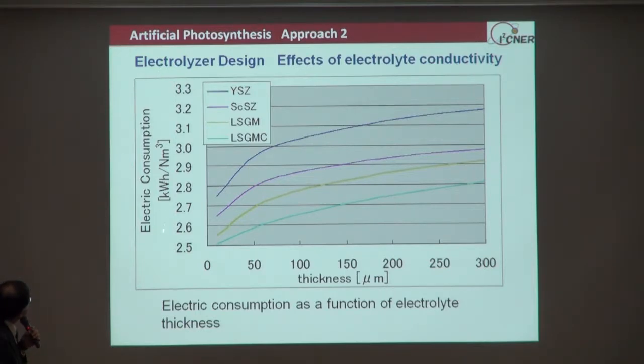This is the electric consumption for the production of hydrogen as a function of the thickness of the electrolyte. And this is the type of the conventional oxide ion conductors. With increasing ionic conductivity, as you can see here, the required electricity becomes smaller. And this LSGM was developed by groups. Therefore, by using this LSGM, we can decrease the required amount of electricity for the production of hydrogen.